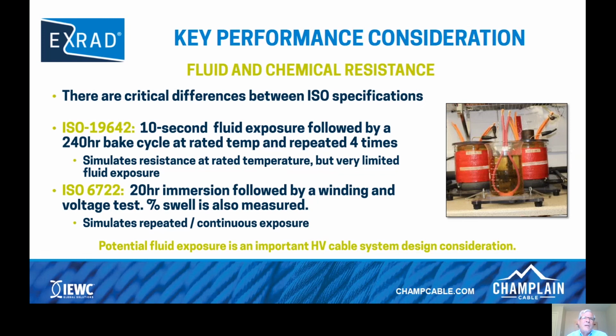Now, what I like about this test is it really is a good test for exposure to fluids like battery acid. Normally, when you do a swell test, which I'll talk about in a second, if you put any insulation into the battery acid, it's not going to react to it for a short period of time. But if you put battery acid onto a cable and then heat it, that rate of reaction goes way up. And oftentimes weaker insulations like rubbers will deteriorate and actually expose the conductor. Very dangerous situation.